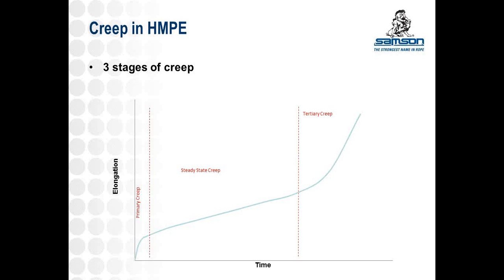After which time the creep rate slows down and reaches that steady state creep, where it's kind of progressing upward at a constant rate. This steady state creep is really the bulk of time. This can be anywhere from weeks to months to years, depending on the specifics of the application. But this is generally where most of the creep strain is taking place.